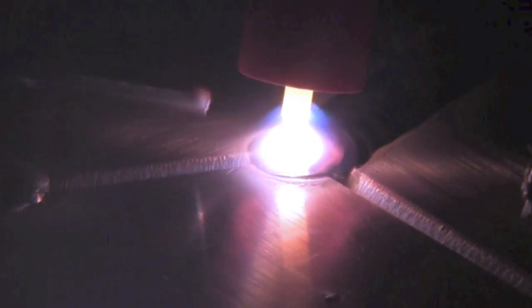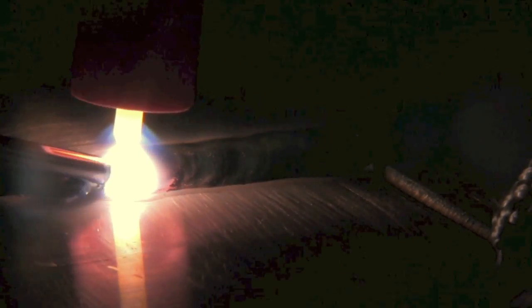Once again I'm set at 200 amps on the machine and probably should have actually just really drove that weld in there a little bit more because it's going to be sanded off. We're going to put a doubler plate over this particular side. For this weld I will drive it in there hard. Maybe a little too hard at times. You can see here in just a second I have to stop and fill in a keyhole. You can't really see the keyhole from the angle of the camera but it opened up with me and I just crammed some rod in there, and I'm really sinking it in there for the penetration.